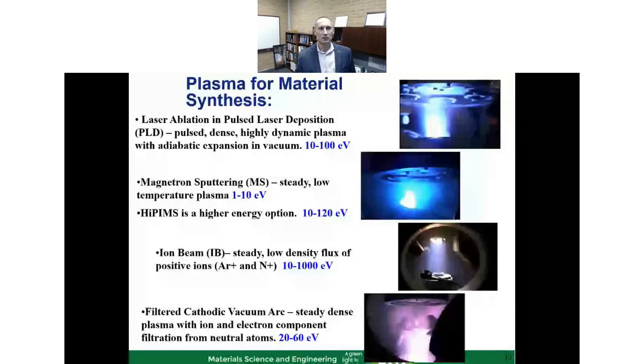And others cannot tolerate the high temperature. So carbon-based materials, or to some degree chalcogenides, will require a reduced temperature. To overcome that, we're using these high energy fluxes and these techniques. For example, in the magnetron sputtering option, you can have a regular one, or you can have a HiPIMS option, and you can bump up the energy of the incoming flux by an order of magnitude, which you then compensate for the low temperature, and you drive the formation of the normally high temperature phases at reduced temperatures.